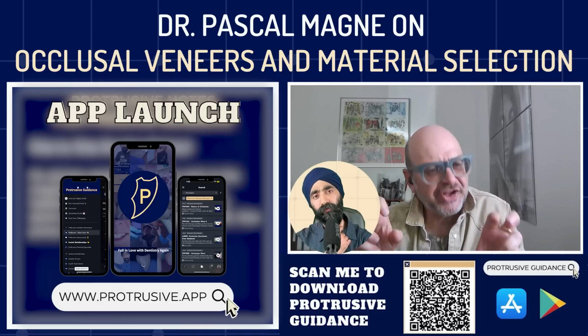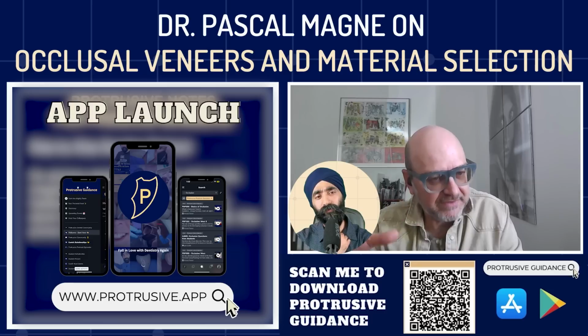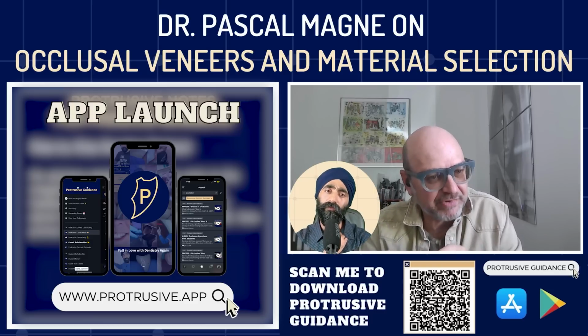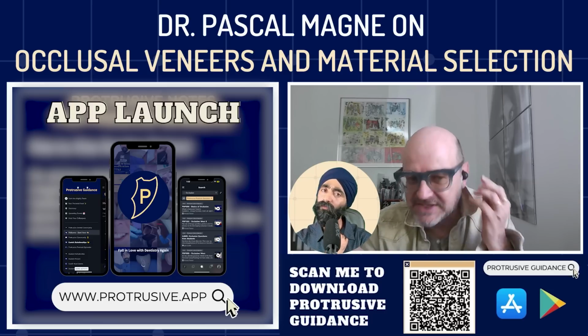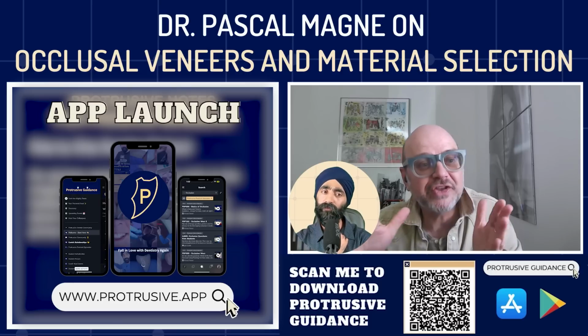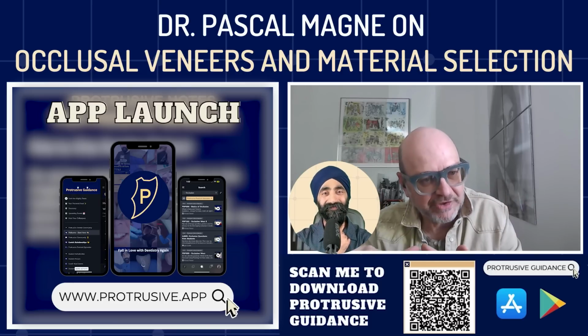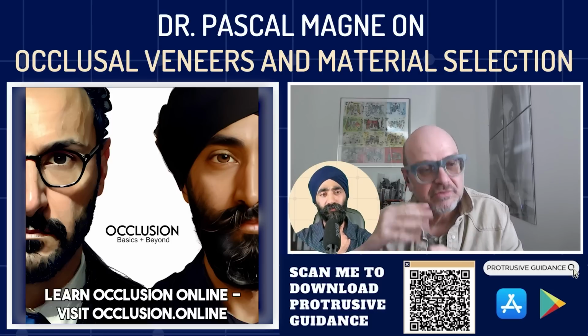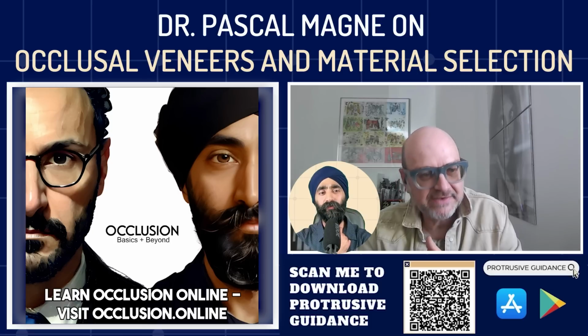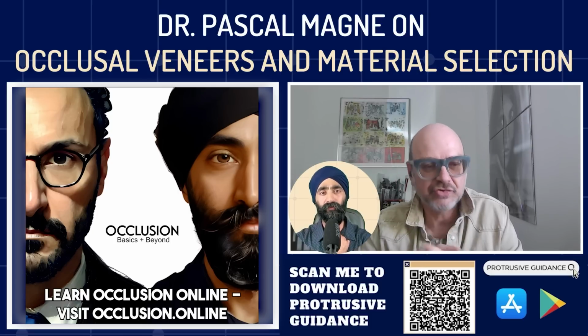Unless you noticed that you have missed some dentin. In that case, I would apply the primer. But if there is no dentin exposed because you did such a good IDS, you don't need the primer the second time. So etch, air abrade, etch, rinse, dry, apply adhesive resin, no polymerization, you don't need.